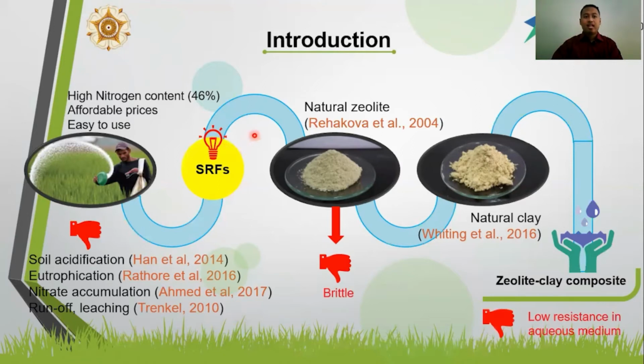This study aims to maintain the initial form of urea fertilizer granules to be encapsulated using a physical barrier. We use natural zeolite because zeolite is abundant in nature and has potential to be used as a physical barrier. We also add natural clay to zeolite, resulting in better agglomeration character of the aluminosilicate framework and increasing the mechanical strength of the zeolite clay composite. However, the zeolite clay composite shows hydrophilic character and causes low resistance in aqueous medium.